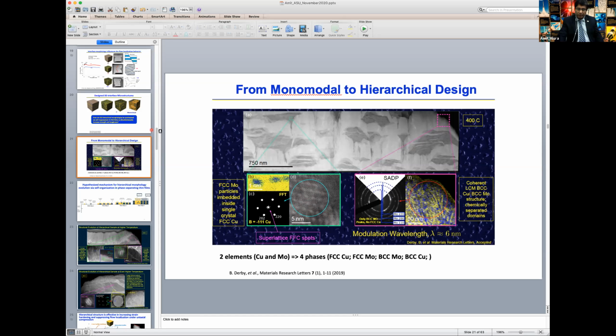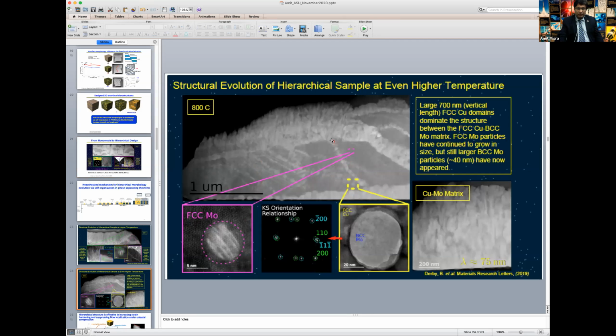But why is it so regular? And why does it go from this to the linear? You have these dots that are lining up. When does it form a linear row of dots versus a three-dimensional arrangement of those precipitates? Those are also different kinds of spinodal. The length scale is not something that a phase field simulation would predict. This is an atomistic scale defect or substructuring that you're looking at. So do you think a method like KMC or, I don't know, phase field crystal would work much better in this context? It could be, yeah.